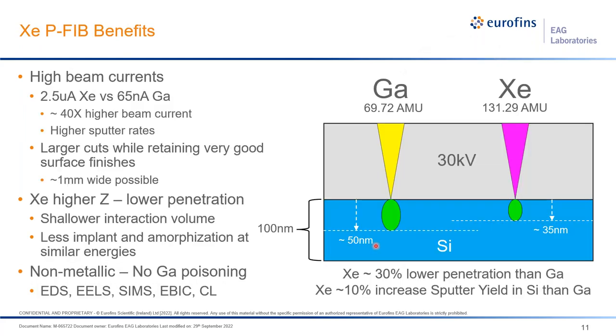So there are three main benefits of using xenon and P-FIB that we're going to cover today. First, in P-FIB with xenon, we have access to approximately 40 times higher beam currents than with gallium instruments. So this leads to higher sputter rates, which enables larger cuts up to about 1 millimeter wide, all while retaining very good surface finishes that are actually comparable to gallium FIB.